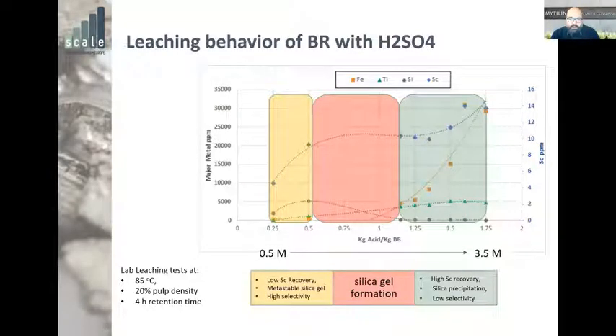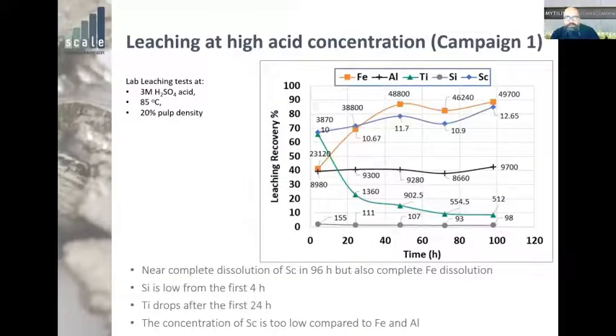And if you're wondering what the scale is in terms of molarity, we are discussing here from half molar sulfuric acid up to 3.5 molar sulfuric acid solution. So we went to the green area and did our first campaign. We extended the leaching time here with a 3 molar acid solution up to 96 hours. And you can see the trend of the various elements.